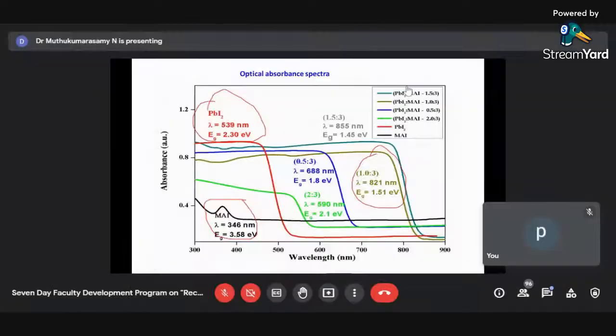Then we did the other characterization studies, and we were able to see that when we had 1:3, the optical window, up to 800 nanometer, the absorption of visible light is very, very good. This one had a band gap of 1.51 electron volt. You can see lead iodide here, this red one, this is the absorption spectra. It absorbs light only up to here, 450 or so, band gap 2.3. And methylammonium iodide, you can see absorption is not very good. The absorption is less than 0.4, and it has a band gap of 3.5 electron volt.